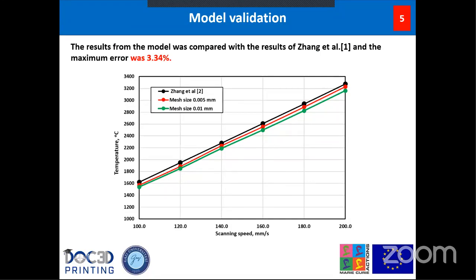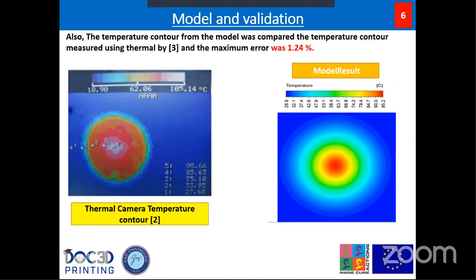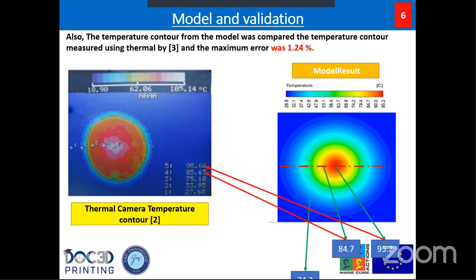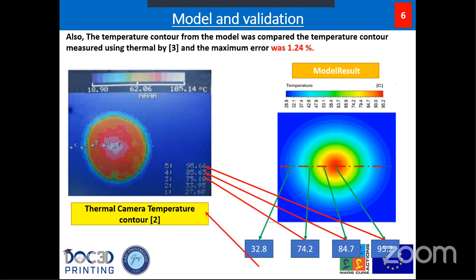For the model validation, we validated our model with data available in the literature, using the work of Zhang, and we found very close agreement between the 2 results, with a maximum error of 3.34%. Also, we made another validation with another study where we compared the temperature contour from the model with the contour from a thermal camera, and we found very close agreement between the 2 results, as you can see.